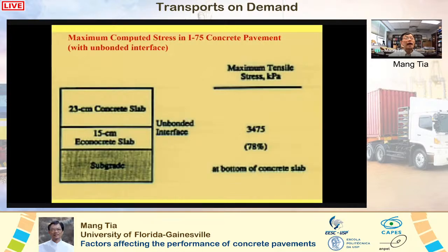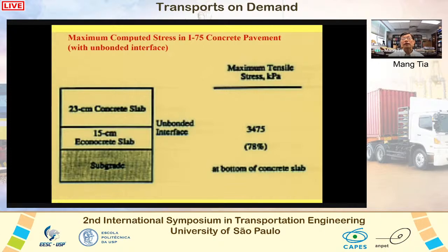The design of the I-75 concrete pavement in Sarasota and Manatee counties is shown on the left here. It had 23 centimeter of concrete over 15 centimeter of Econocrete base, and there was no bonding between the concrete and the Econocrete base. Critical stress analysis using a 22 kip axle load and a temperature differential of plus 20 degree Fahrenheit in the concrete slab gave a maximum stress at the bottom of the concrete slab, and the stress was equal to about 78% of the flexural strength of the concrete.